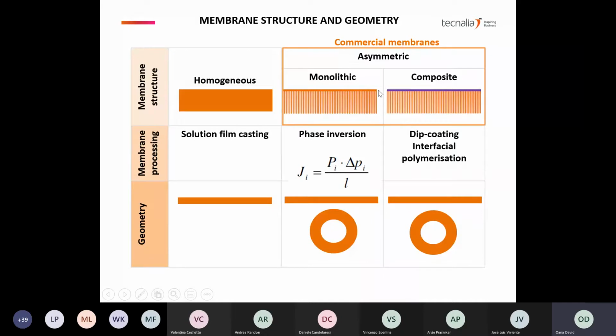If the top layer and the porous support are made from the same material, then they are defined as monolithic membranes and are made by phase inversion in a single-step process. And this is highly desired because it's very simple. In contrast, when the material cannot be made by phase inversion into a membrane, it has to be coated on a support that was previously made, either by dip coating, or it has to be synthesized in situ by interfacial polymerization.